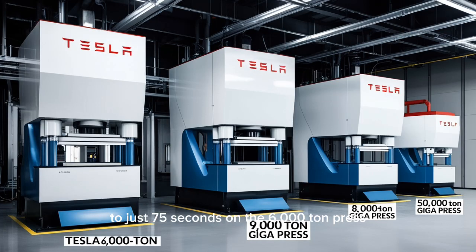It's now 7 kilograms or about 15 pounds lighter than before and needs 50% less machining time. This 15% weight cut gives better performance and longer range, plus a stiffer back section that reduces twisting when turning sharply. Since 2020, the Giga casting process has come a long way. Tesla now uses custom cooling channels that follow the mold's shape, which slashes casting time from 170 seconds to just 75 seconds on the 6,000-ton press. Thanks to that, Model Y became lighter, more exact, and more consistent.